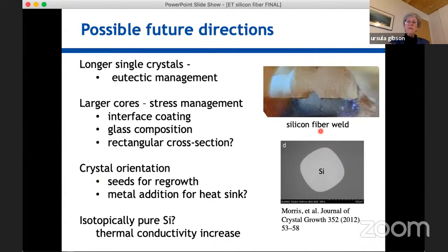The other thing is that we found that this business of drawing a metal through the core is actually a zone refinement technique that is known to the silicon industry. And these fibers are sort of the perfect geometry for that. So if we need to, I think we can do a multiple pass refinement and get the purity very, very high. Thank you.